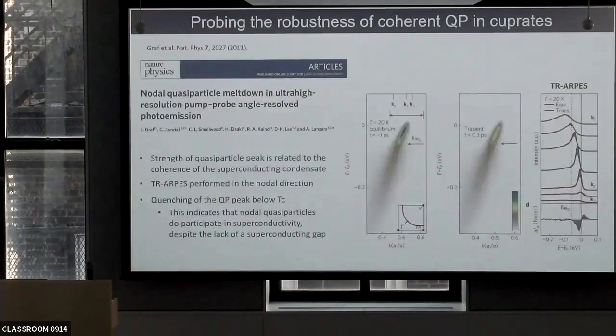Yet another way now is not just melting a CDW and then mapping a band structure, but really changing the character of a quasi-particle. This is a bismuth cuprate, work done in Lanzara's group, where you have a dispersion, the single dispersion for a copper-oxygen band here. And what you do, you come in at some delay with a pump, and then you probe, and you can see just from the color that something has changed here.